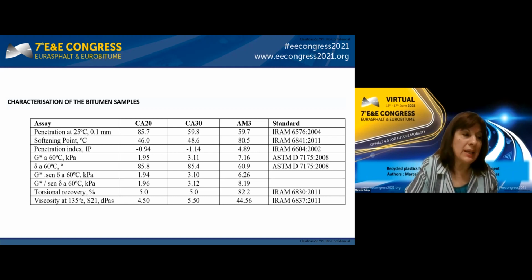The previous test showed that a level of 4% of PE when added to the CA30 bitumen did not always result in homogeneous distribution of the PE material. It was also found that adequate mixing temperature, speed, and time are key variables in the mixing step to get a homogeneous final product. It was concluded then that the CA20 bitumen was the best option to incorporate the recycled plastic in order to get a compatible plastic bitumen mix.